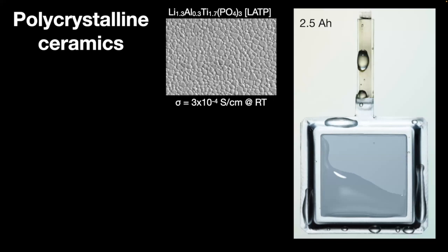For a material with such a high lithium ion conductivity and a large population of lithium ions, it's an unexpected property, and it allowed Polyplus to develop this very unusual water-stable lithium metal electrode. You see that on the right. And these are really water stable. We can put that electrode, which is sitting at the lithium potential, in water for certainly in excess of a year. We've done these kinds of tests with a self-discharge rate of zero.